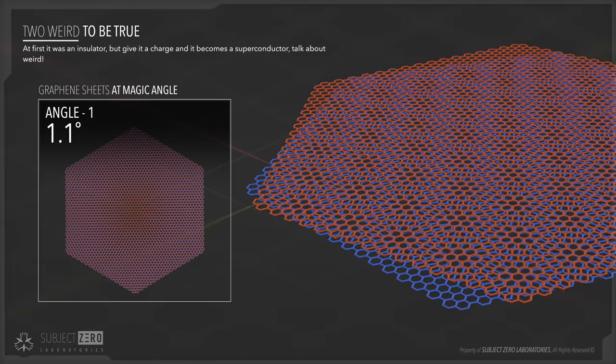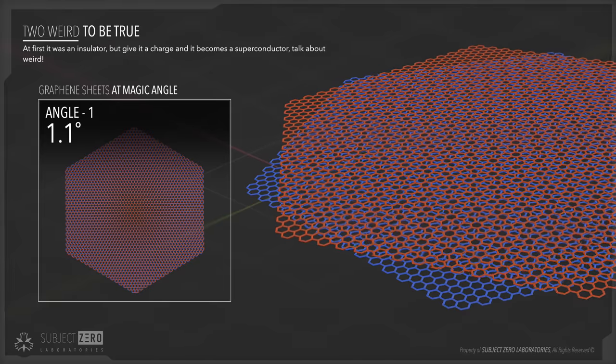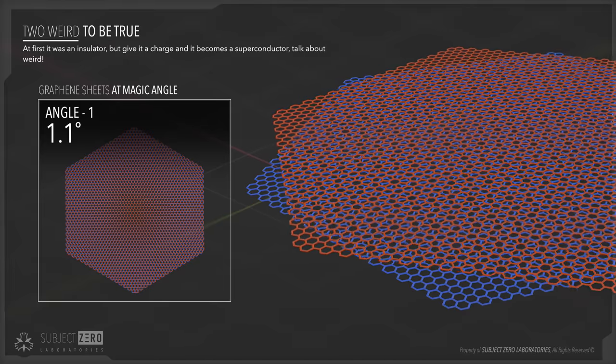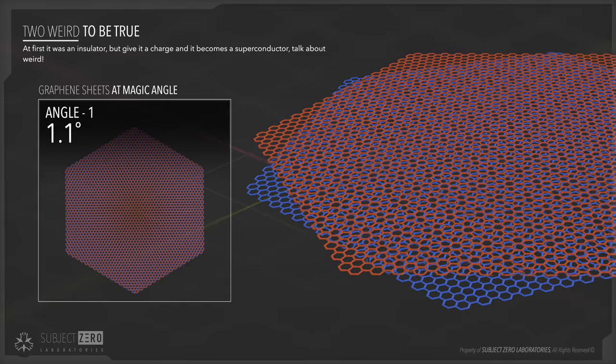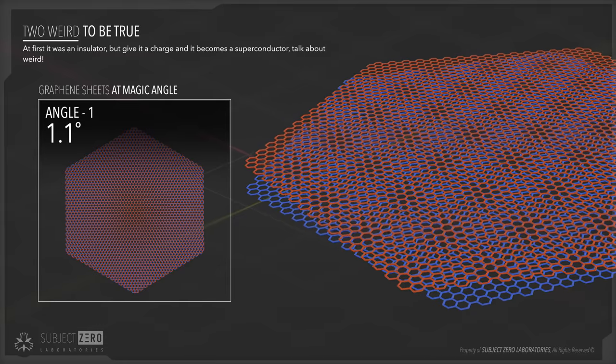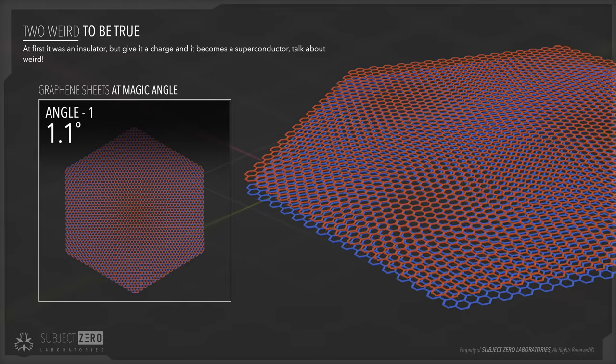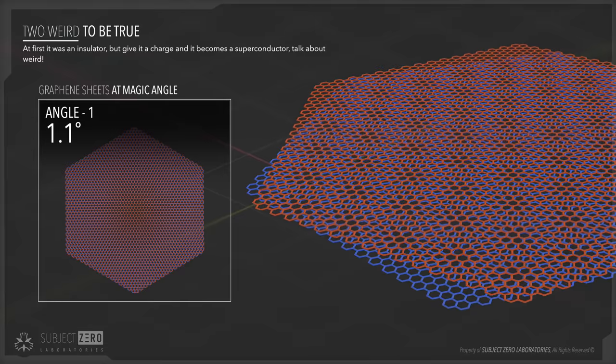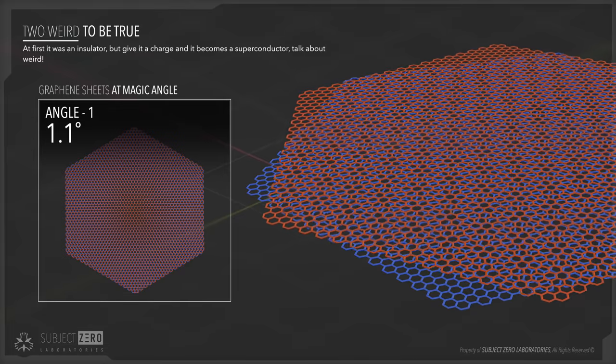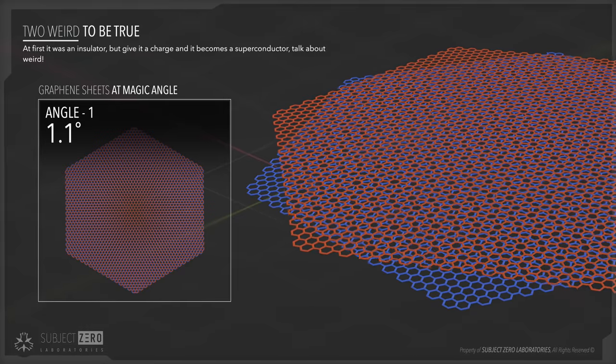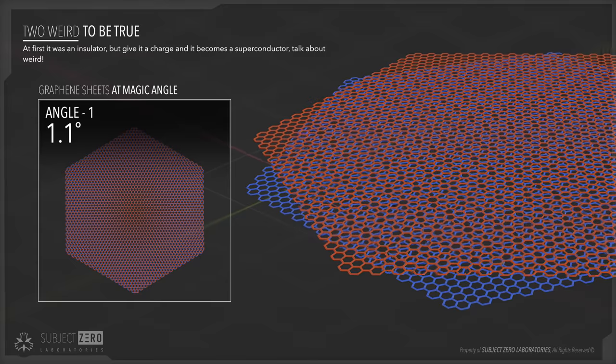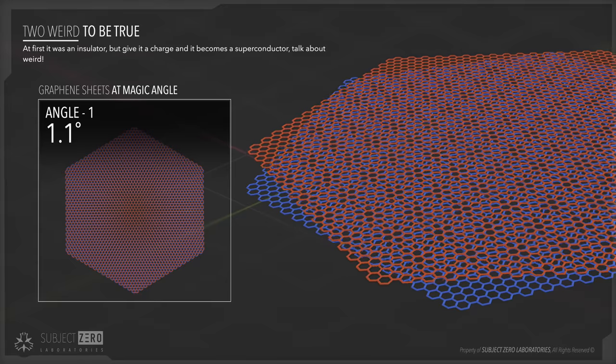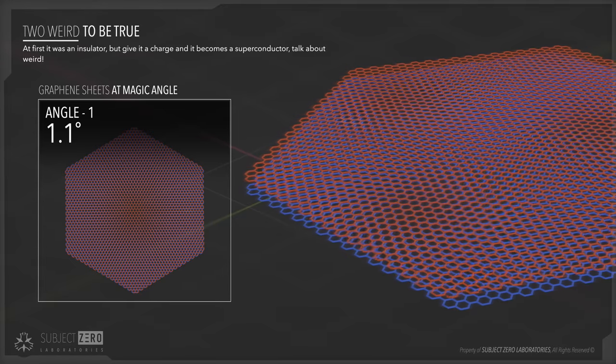To see if the effects would be the same at any voltage, they increased the electrical field to pump up just a few extra charges into the sheets, and that is when graphene became a superconductor. The important thing here is that every experiment afterwards confirmed that this was in fact happening, not only at MIT, but also in Harvard and other universities.